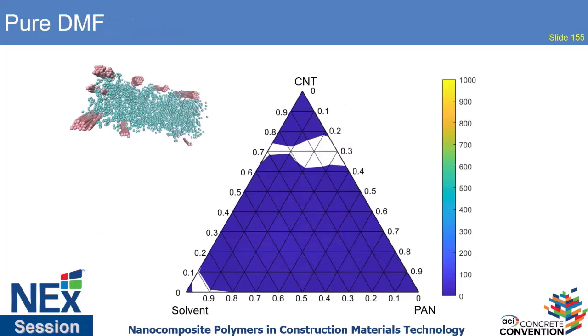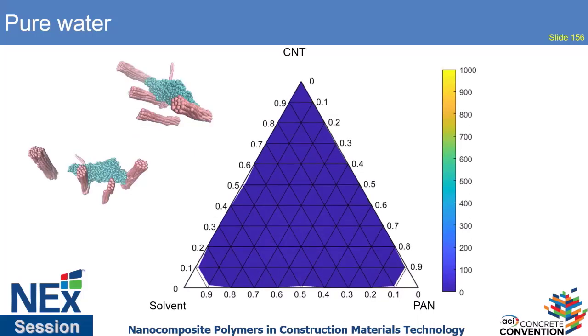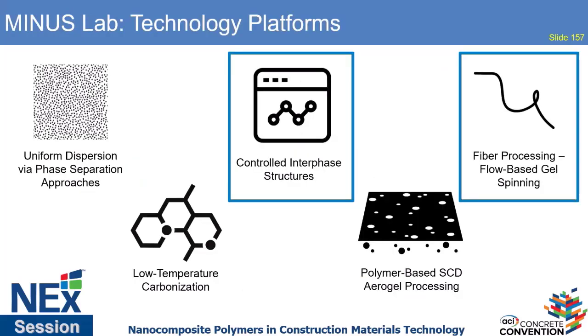And what we find is that if I'm working with one particular polymer, a solvent that's great for the polymer is not so great for the nanotubes. If I work with a non-solvent, then the two of them are running away from each other because they hate the system. So finding the right balance between the solvent-non-solvent mixture is actually the sweet spot. And so these phase diagrams have given us insight. So that's a bit about how we're using this dispersion. So I'll move now to how we're using that to put into the composite.